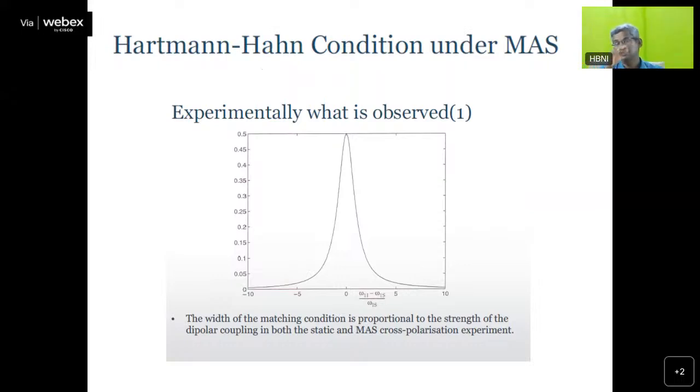So I mentioned here that we are doing two things: one is cross polarization and another is magic angle spinning, CP-MAS. CP stands for cross polarization, MAS stands for magic angle spinning. But one problem with MAS, which I told in the first or second class, is that MAS averages the dipole-dipole interaction. Why is it getting averaged out? Because the dipole-dipole interaction has an angular dependence, a term called 3 cos squared theta minus 1, which is part of the dipolar Hamiltonian.